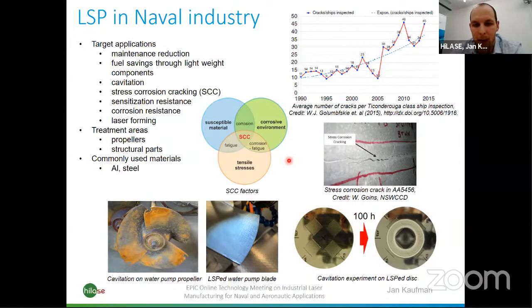Another area where you can use LSP in the naval industry, this is something we have actually done at Hilase, is to reduce cavitation effects. Cavitation is basically when you have these low pressure bubbles imploding against, let's say, a ship propeller. This is the damage it does. So what we've done, we took a water pump blade and we peened it over here where the cavitation is most severe. And when we had done some experiments beforehand, we peened this disc over here. You can see these 4 LSP patches, and we subjected it to cavitation for a period of 100 hours. And then we measured what the cavitation did, and we found out that the mass lost due to cavitation, and also the depth of the cavitation, was halved in both cases.